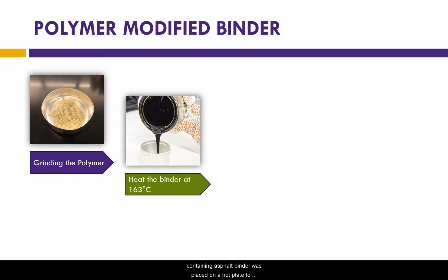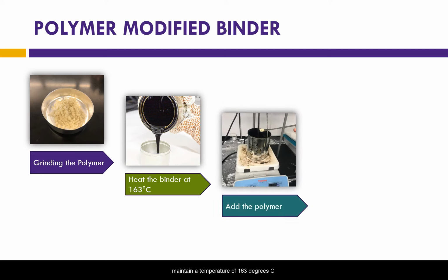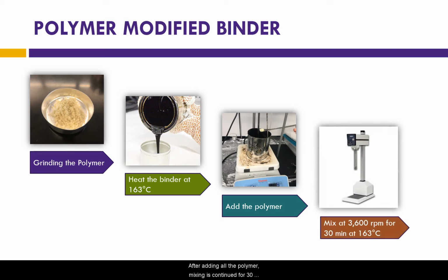The metal can containing the asphalt binder was placed on a hot plate to maintain the temperature of 163 degrees C. A high shear stirring machine was used to provide an RPM of 3600, and then polymer was added to the binder slowly. After adding all the polymer to the asphalt binder, mixing is continued for 30 minutes at 3600 RPM and 163 degrees C.